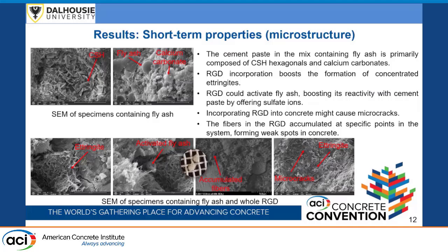So based on the SEM pictures, we can see that the cement paste, without any RGD, is primarily composed of CSH and calcium carbonate. But when we add recycled gypsum drywall, we can see some ettringite. So we have concentrated ettringite in the SEM pictures, so it promotes the formation of concentrated ettringite.